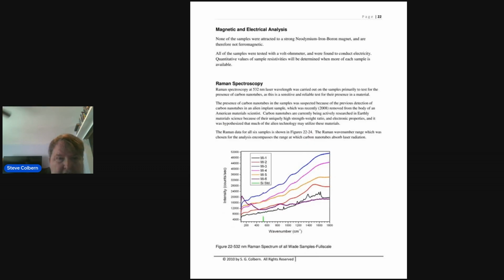And magnetic and electrical analysis. I tested all the samples with an ohmmeter, and they all conducted electricity. And none of them were attracted to a neodymium iron boron magnet, so they weren't ferromagnetic. I'd be surprised if they weren't a little paramagnetic because they had significant amounts of iron in them, as evidenced by the ICP-MS. But I wasn't able to determine quantitative values of sample resistivities because the samples are sort of irregular in shape and thickness. But if we do any more testing, we could probably figure that out.